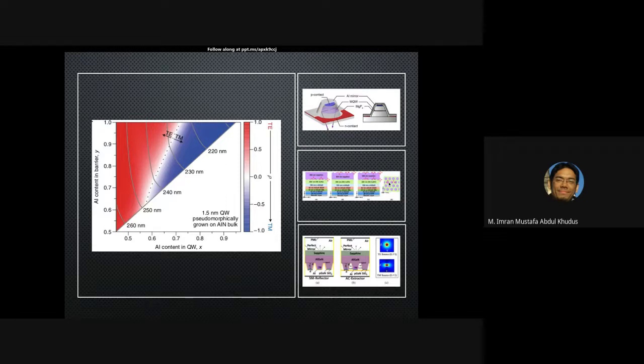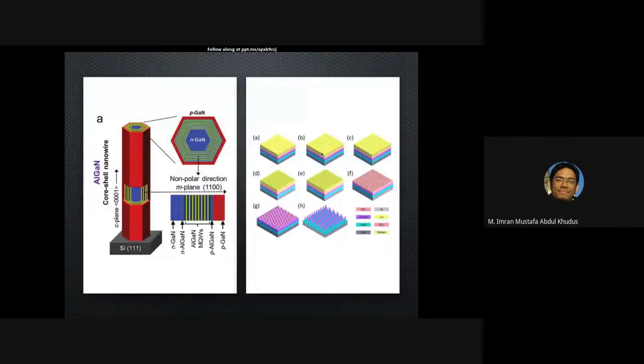So this is a photonic crystal. They did a photonic crystal on this, and the reason they do this is to coax some of the TE and TM light out, to improve the light extraction efficiency. This is another method. This is using core-shell nanowires, right? A little bit out there. Not that many people are doing it. That's not true, some people are doing this.